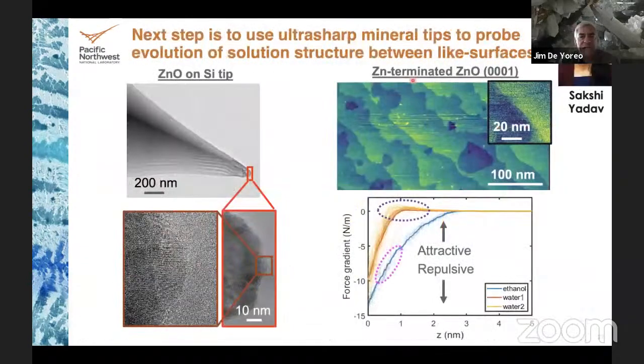So what that tells us is we have to use the same chemistry as the material we care about. And so we're now making single crystal tips of the same material that we want to measure with. And here's a beautiful zinc oxide tip. You can see this is the bump on the end. It's a sputter deposited zinc oxide on a commercial silicon cantilever AFM tip.